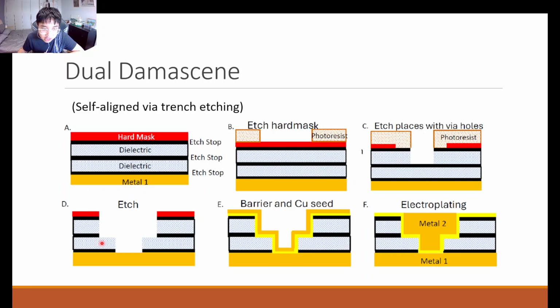Once we successfully conduct the self-aligned via and trench etching, we can lay down the barrier layer and the copper seed and then electroplate. So why do we need the barrier layer? The barrier layer is often a conductive nitride, such as titanium nitride or tantalum nitride. The reason we need the barrier is because copper has a pretty high solubility and mobility in silicon. We do not want our copper atoms diffusing into the dielectric and then into silicon and altering the electrical properties of the silicon semiconductor. That is highly undesirable, so you need a barrier layer to prevent this kind of interdiffusion from happening. And then a seed layer is needed for the electroplating process later.